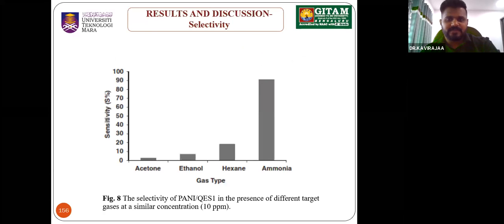Next slide. Okay, for the selectivity, we tested with some common interfering gases, and we realized that it showed higher selectivity for ammonia, probably because of the ion-dipole interaction between the PANI composite and the ammonia. Next slide.